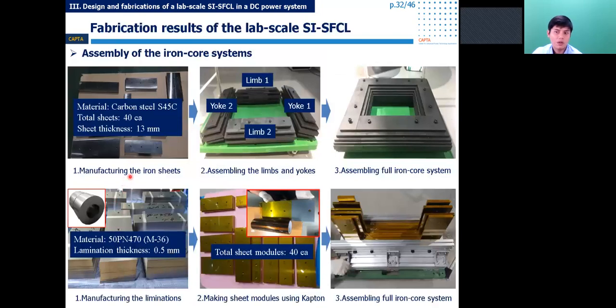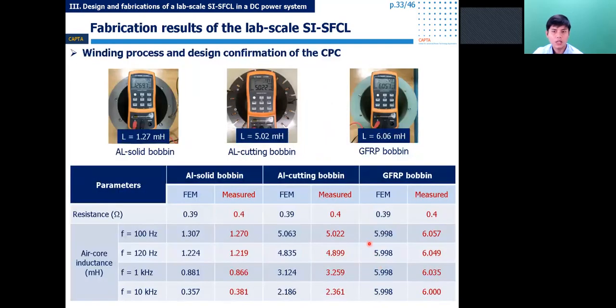After designing the components, the lab scale SFCL was fabricated. Firstly, the iron core system. Here we selected the two types of iron core, S45C and M36 core. They were already manufactured and assembled. In case of the primary coil, it was wound on the 3 kinds of bobbin in the design. The parameters of the primary coil were measured and compared with the FEM simulation. In the result, you can see the measurement result and the FEM simulation were similar.